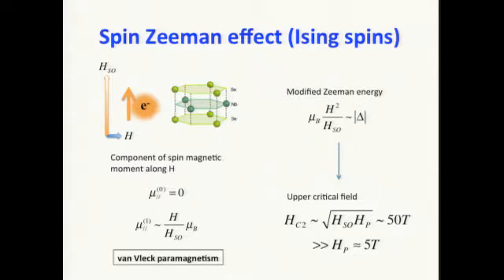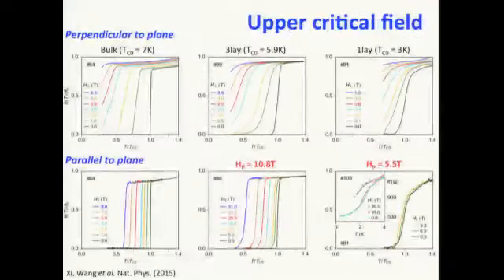This is not the full picture, which I'm going to tell you. This is a somewhat naive estimate. So with this picture in mind, it basically explains the observation of the parallel magnetic field data in this case. And for the trilayer and the monolayer, I also write down their HP value, which is 10.8 Tesla and 5.5 Tesla. So you can see that because of these Ising spins in the material, the upper critical field gets way beyond the HP value of each of the materials.